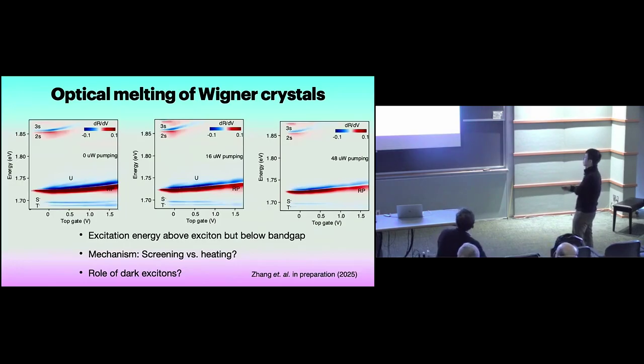Okay. So because we are exciting below the band gap, we are not creating free carriers directly. You can also see that there is no shift in the repulsive polaron branch. Of course, we are also generating heating, but by looking at the position of this repulsive polaron, we find that this disappearance of the Wigner crystal is not entirely due to heating. There is actually an additional screening effect.